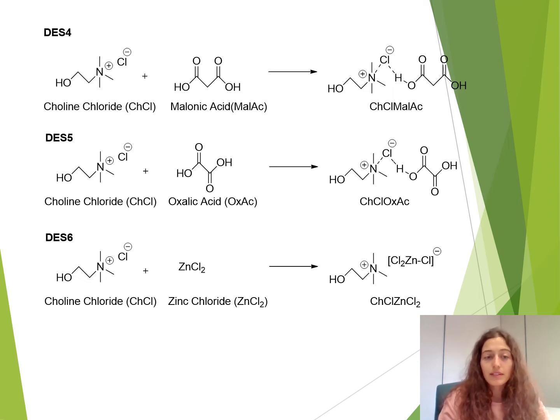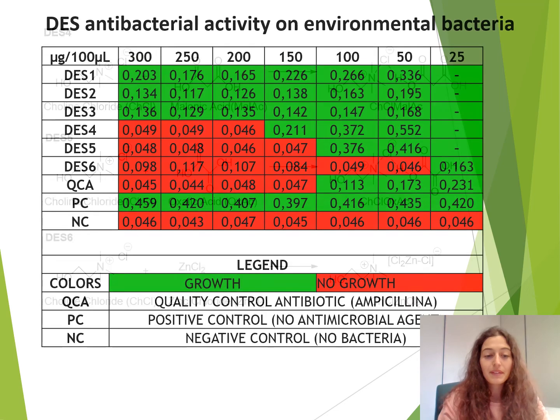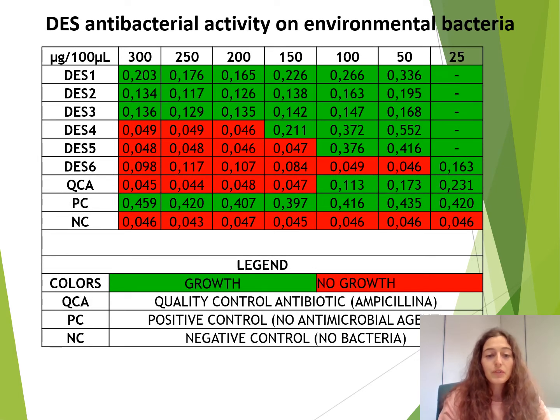Deep eutectic solvent 6, choline chloride zinc chloride, has a high viscosity at room temperature. Therefore, choline chloride zinc chloride was synthesized diluted with 1 ml, 2 ml, and 3 ml of double distilled water. This table shows the antibacterial activity of each synthesized deep eutectic solvent tested on environmental bacteria. Deep eutectic solvents 1, 2, and 3 did not show any antibacterial activity.